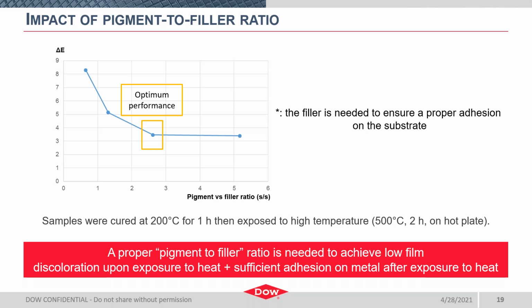Although it appears that eliminating the silica altogether would maximize heat resistance and color retention, our testing does indicate this formulation does require at least some silica for initial and post-heat wet and dry adhesion to a steel substrate. And if we want to minimize color change and maximize post-heat adhesion, of course, a pigment to silica ratio of approximately 2.5 gives us that best balance.